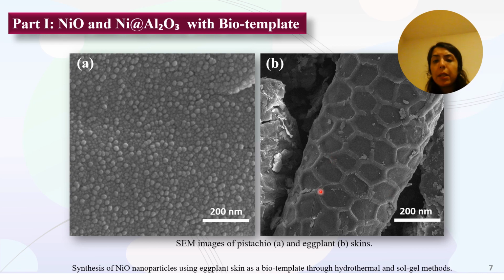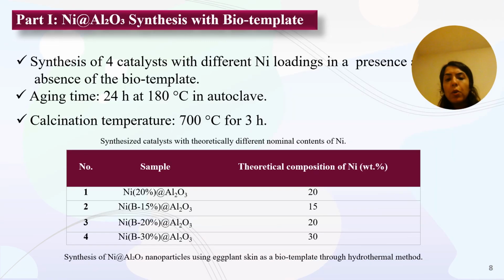The first image is related to pistachio skin, which had a dense structure without any porosity, and the second one is related to eggplant skin, which had a tube structure and some hexagonal shapes on it. So we chose eggplant skin as a biotemplate. For this experiment, we synthesized three catalysts with different contents of nickel and one sample without biotemplate to compare their results.